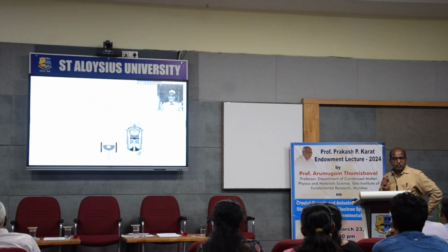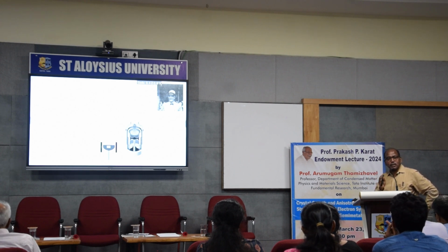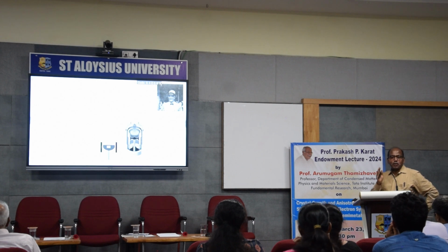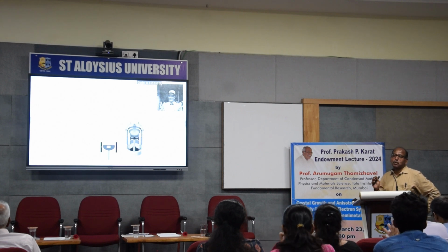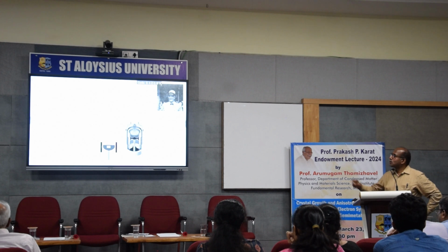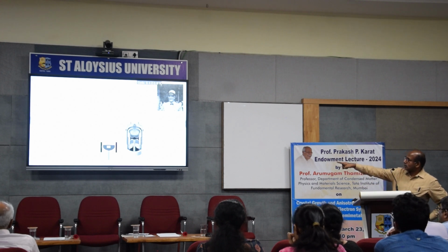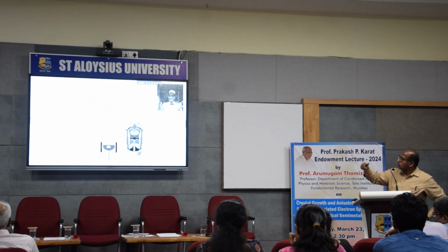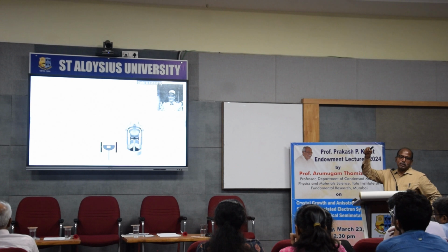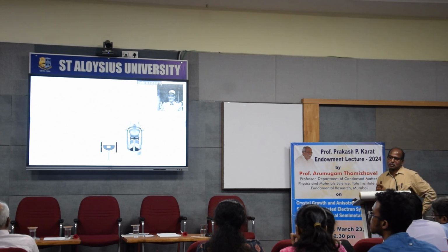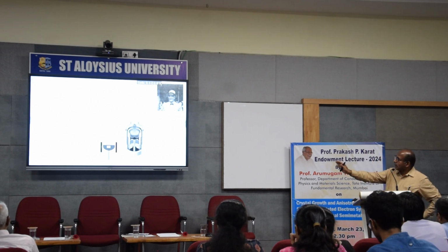So he did an X-ray diffraction of that, and he found spots. I told you anything where you get a diffraction spot is a single crystal. So he found that tin samples can be grown by slowly cooling. Then he designed the one shown on the left-hand side, in 1917. He designed that furnace to melt a metal, insert a seed crystal, and slowly pull it out. So you can get single crystals of these materials. So that was in 1917.